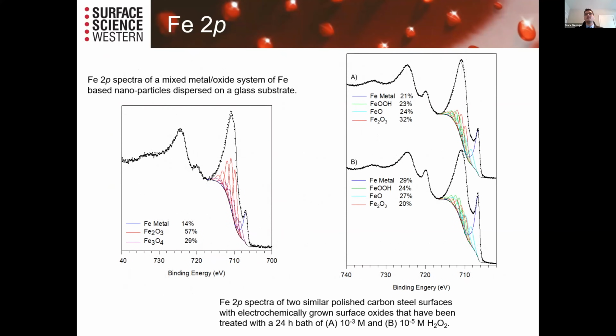If you look at the peaks, it looks like this all kind of looks the same, but there's enough change in the structure and enough change in the binding energy shifts that we can pull out the different amounts of things that are present here. So here we have Fe3O4 and Fe2O3, but over here we have FeO and Fe2O3. If you're looking at a series of samples such as these, you can really see changes, and you can prove to yourself, yeah, this is working. We are seeing these changes within the peak structures, and being able to quantify to a degree what we have in these species.